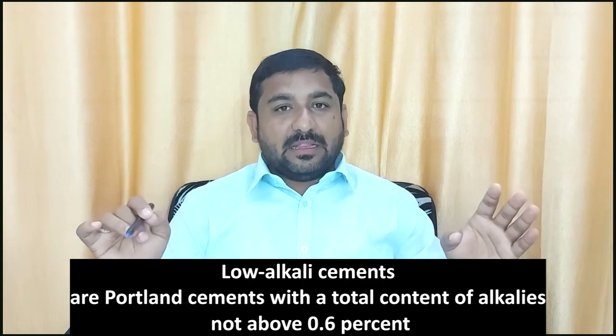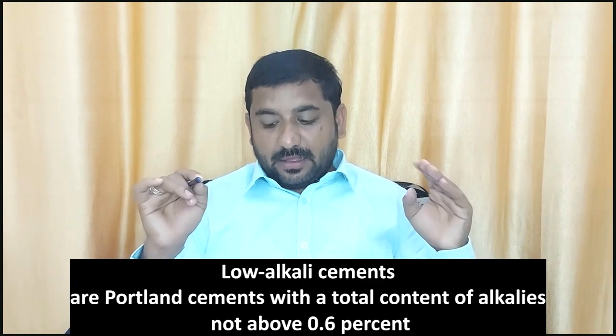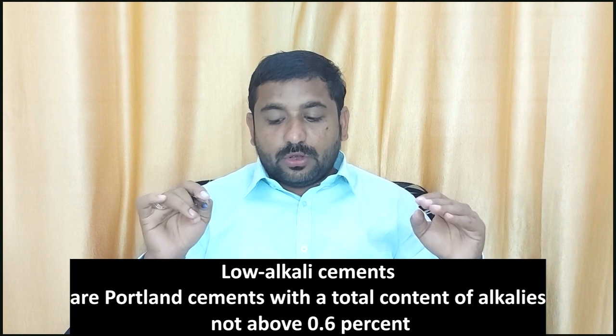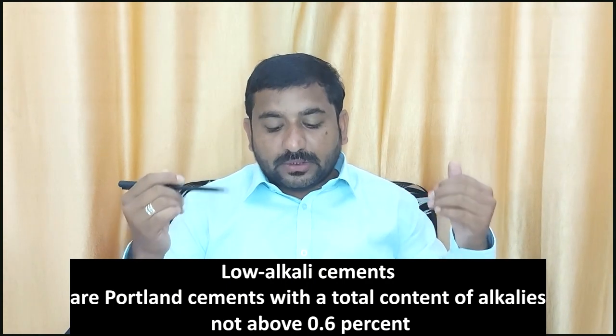That aggregate is expensive. So to overcome the alkali aggregate reaction, again we have to turn to the GGBS. What happens here is the replacement of cement up to 30-50% by the GGBS, using a low alkali cement. So now the question is, what is the low alkali cement? Every cement available in the market has an alkali ratio, but the alkali ratio should not be more than 0.6%.